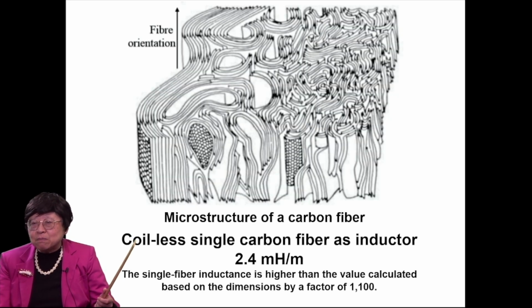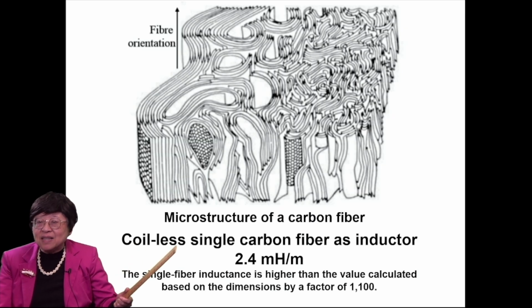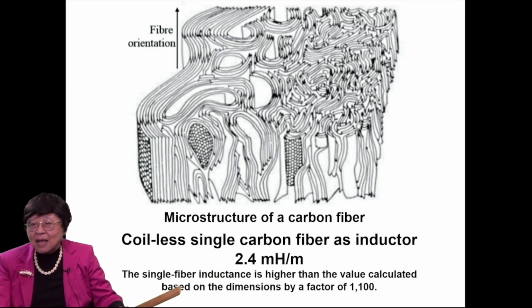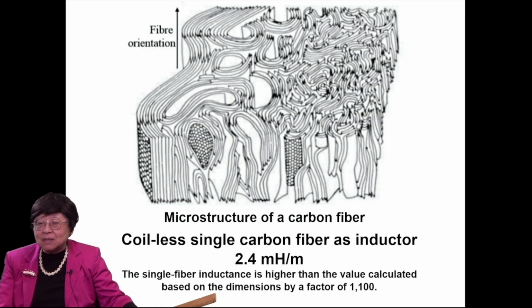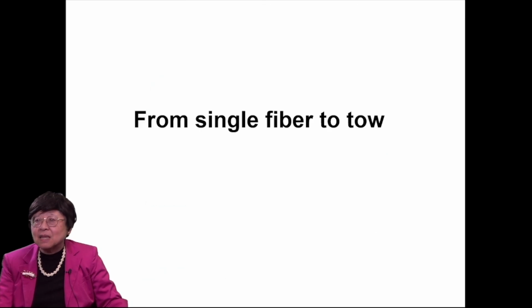So because of this microstructure, the coilless single carbon fiber as inductor provides 2.4 millihenry per meter of inductance. And this is higher than the value calculated based on the dimensions by a factor of 1100. So this high permeability is almost all due to the microstructure.